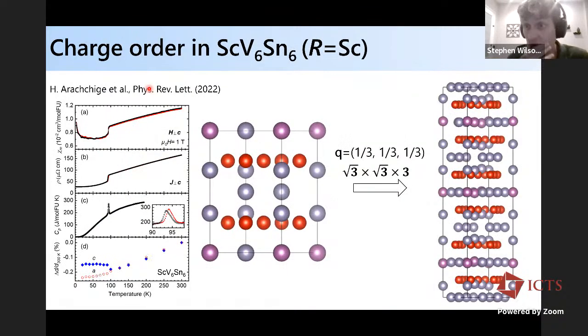But David Mandrus's group at the University of Tennessee, instead of putting yttrium in, put scandium, which is a smaller ion. And when he did that, if you look in the susceptibility and resistivity and heat capacity, there's a transition that seems to form around 100 Kelvin. And that transition can be mapped to a single Q distortion of this bilayer lattice at the K point in plane, which has a wave vector of a third, a third, a third, which is a √3 by √3 by 3 enlargement of the unit cell, okay?